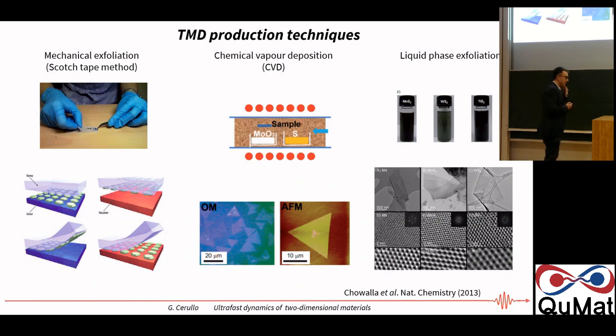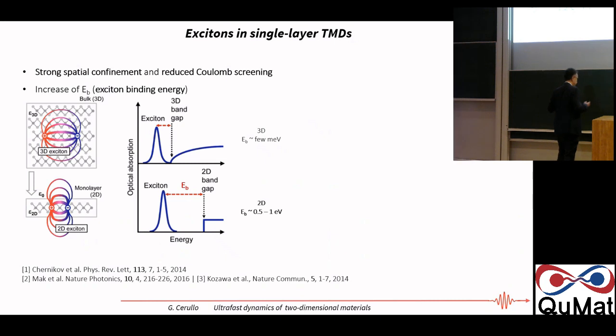But now I want to focus on the really remarkable electronic and optical properties if you compare them to a standard semiconductor. So the first striking property that you have is that you have strongly bound excitons. If you consider a normal semiconductor like gallium arsenide, if you excite an electron from the valence band to the conduction band, in principle, you leave a hole behind, and you should form what is called an exciton, which is a hydrogenic system where the electron and the hole are attracted. But in a bulk, three-dimensional semiconductor, there is a high dielectric constant of the material, which screens the attractive interaction.